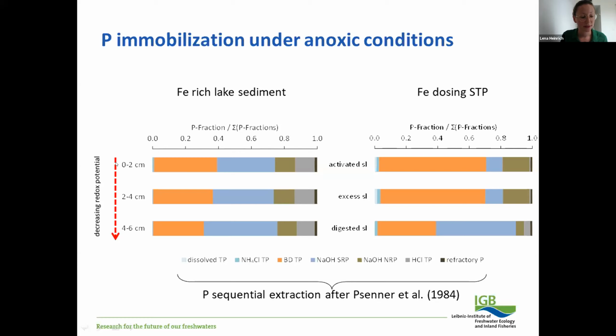And then we analyzed the fresh sediment and sludge by a sequential extraction, which is designed for phosphorus binding forms in freshwater sediments. And I will only explain the most important fractions. Therefore, I would like to direct your focus to the orange and the blue bars. The orange bars here and here indicate redox sensitively bound phosphorus. So the phosphorus that is maximum desorbed from dissolving iron hydroxides and also manganese compounds under anoxic conditions.